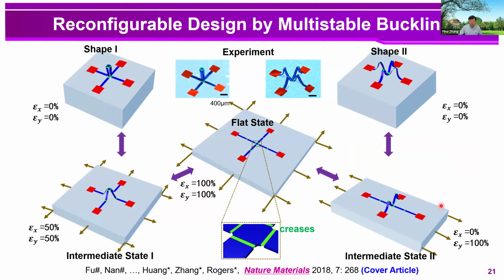Actually, in previous studies, we always release the biaxial pre-strain in the substrate simultaneously. The result is a deterministic 3D assembly, with the smooth changes of 3D shapes. Here I will show that for some specially engineered precursor designs, we can play with the sequence of the release in the pre-strain to achieve multiple stable modes of buckling. So here is an example to illustrate this idea.